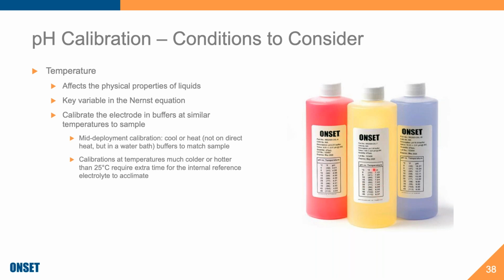So paying attention to what the temperature of your solution is and what the actual pH value should be. This number is usually, and it should be, what's used by the manufacturer to create your slope and your offset. So the answer to the question is definitely pH is important. And one more thing that you can see here is pH 10 buffer from 0 to 45 degrees has a huge variance. I mean, it goes from 10.31 at 0 degrees Celsius to 9.86 at 45.